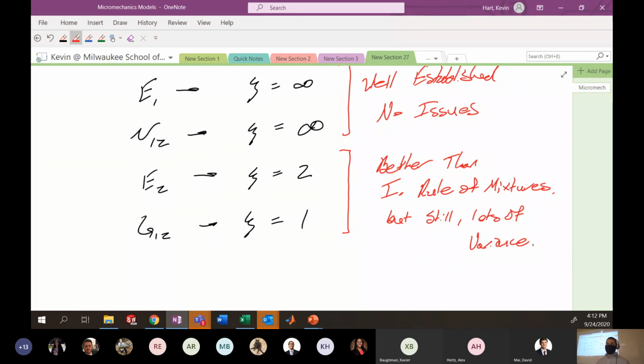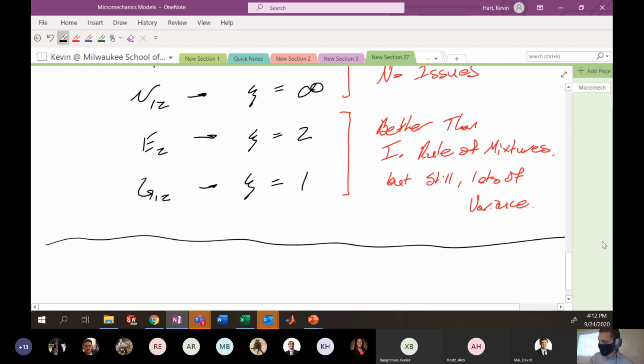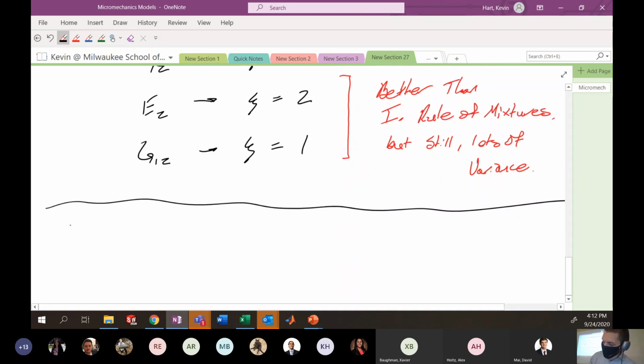That's kind of the way that the world works with this particular equation. It's semi-empirical, and so people make estimates based on a value of psi equal to 2 for the modulus in the 2 direction, but in actuality, it's a little suspicious to just generally assume that. Assuming infinity for E1 and nu 1, 2 is pretty solid, but these guys here, a little suspicious. So we'll just say that. All right. Onwards, an example. Finally, enough talky. Let's do an example.